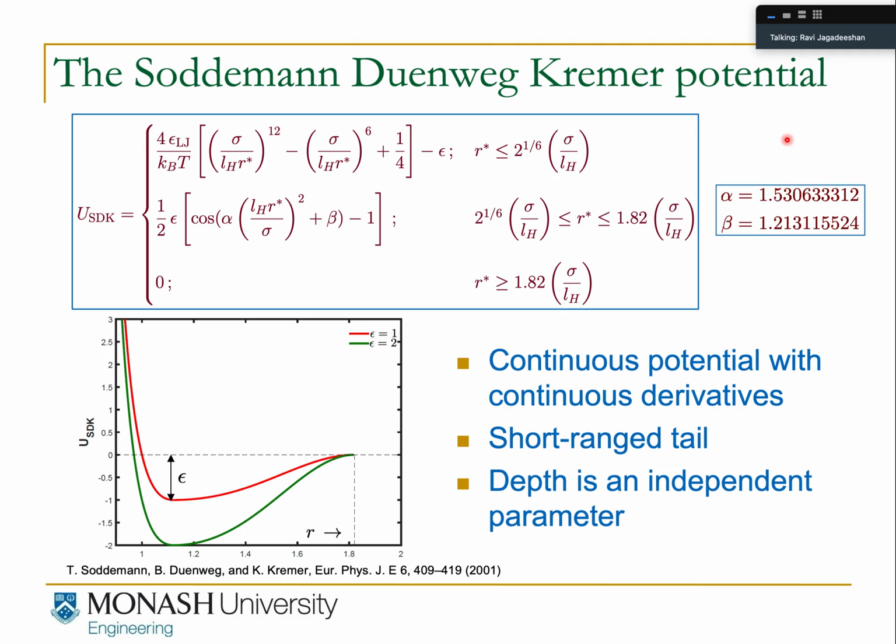This is essentially a modified Lennard-Jones potential where, instead of the infinite range of the Lennard-Jones, there's a sharp cutoff at a finite value, and we can simply vary the attraction between stickers by changing this well depth. So it allows us to simulate both the backbone monomers and the sticker monomers with the same potential, right?